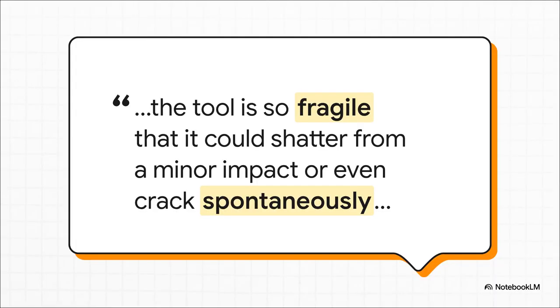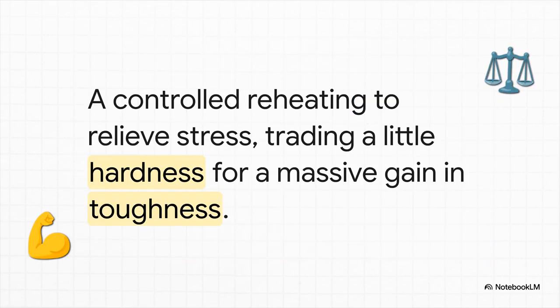And I'm not kidding when I say brittle. As the quote says, the tool is so fragile that it could shatter from a minor impact or even crack spontaneously. The internal stress is just so high that a small bump, or sometimes nothing at all, could make it literally shatter into pieces. So how do we fix this? The solution is called tempering. It's a controlled reheating, but to a much lower temperature this time. What this does is it lets some of that internal stress relax. It's a trade-off, really. You give up just a little bit of that extreme hardness, but in return, you get a massive gain in toughness.